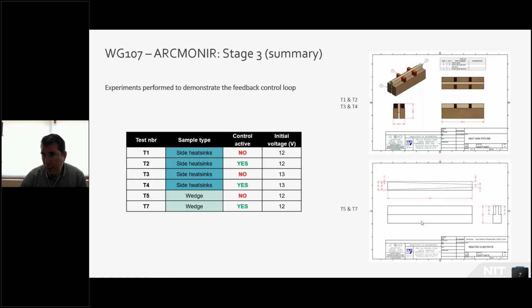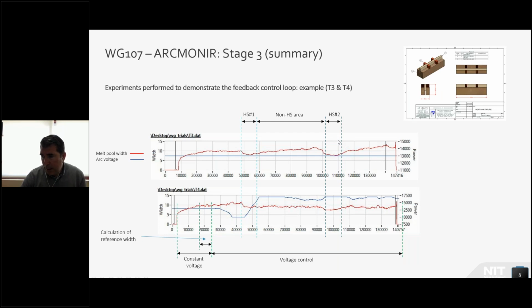The experiments that we did, once we had integrated the camera and were sure that the closed loop control of the voltage was working, were a couple of experiments just to demonstrate the feedback control loop. In this case, we used the samples again with the 2 side heat sinks because we want to see if the camera is capable of controlling the melt pool width in these areas. And we also used a wedge sample, which is increasing the area, and this has, of course, the area of diffusion, and it has an effect on the melt pool width. Just to simplify, I'm going to show you the results of the experiments T3 and T4, which are shown in this slide.